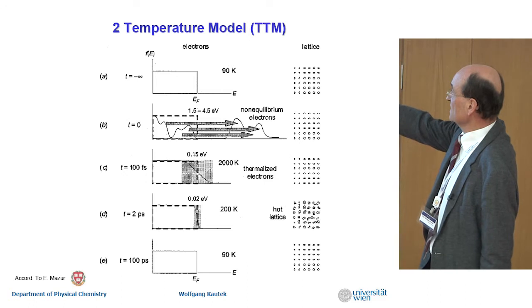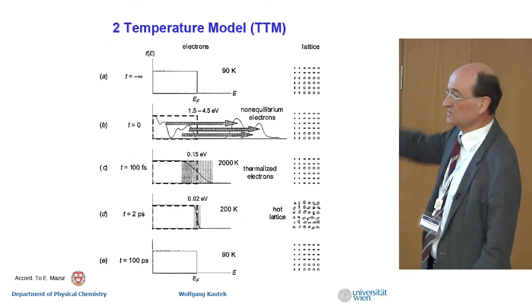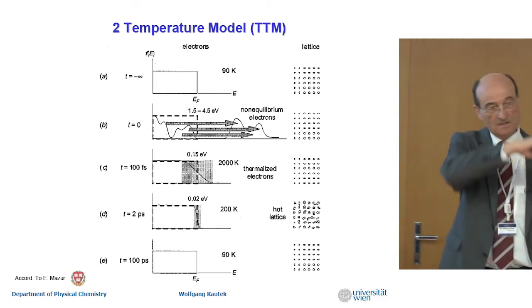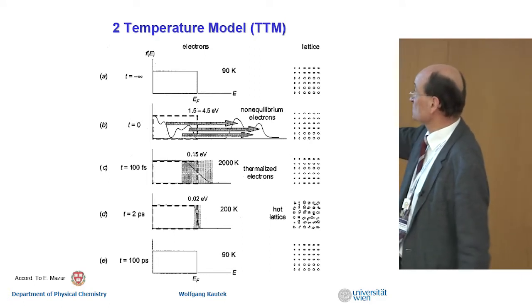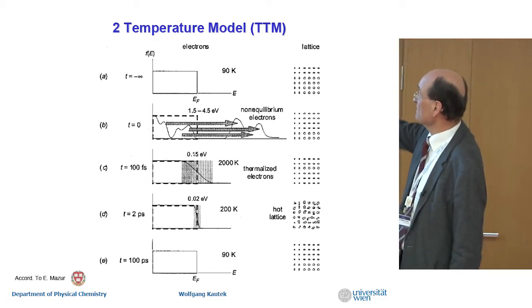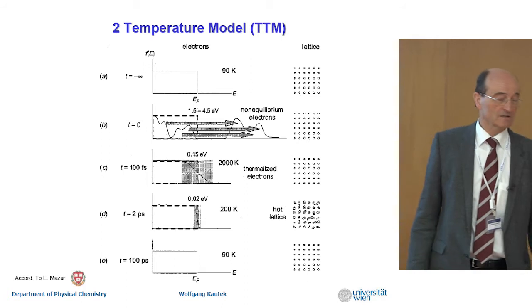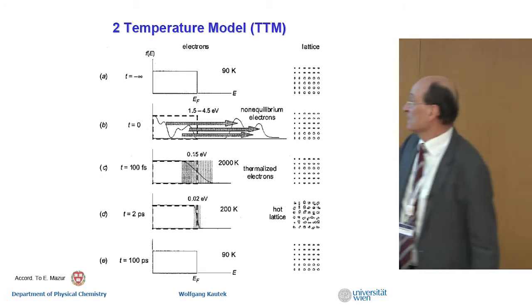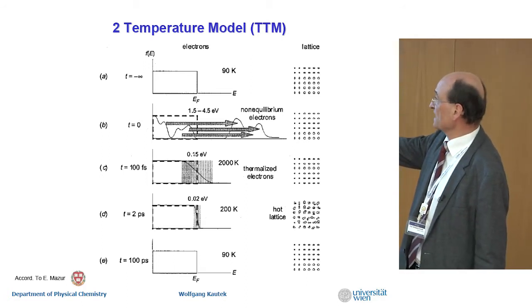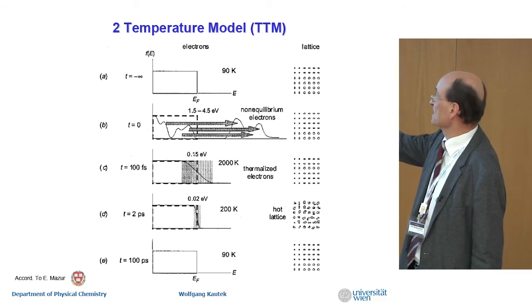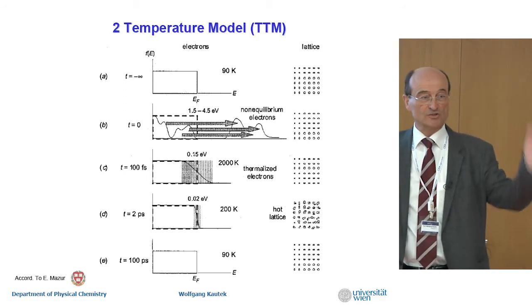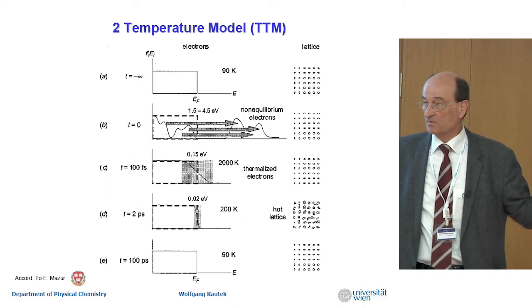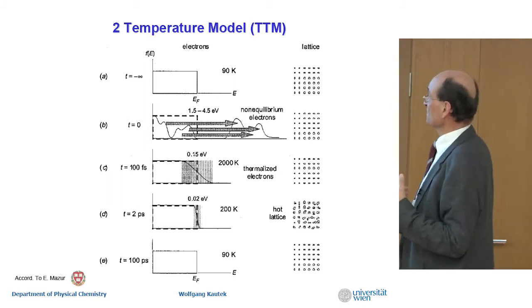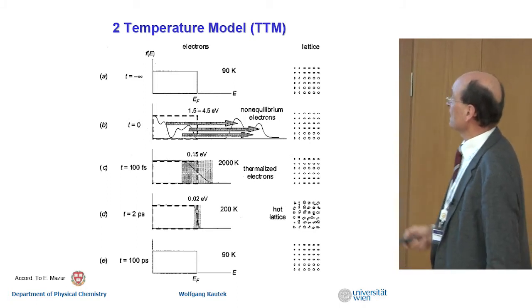Then after the scattering of free electrons, you have a distribution. So the distribution function is spread around the Fermi level. Electrons hot, the lattice is still cold. And then at the electron-phonon relaxation time of a couple of picoseconds, the lattice is hot and the electrons are in equilibrium with the lattice. So that's what we are playing with at short pulses.